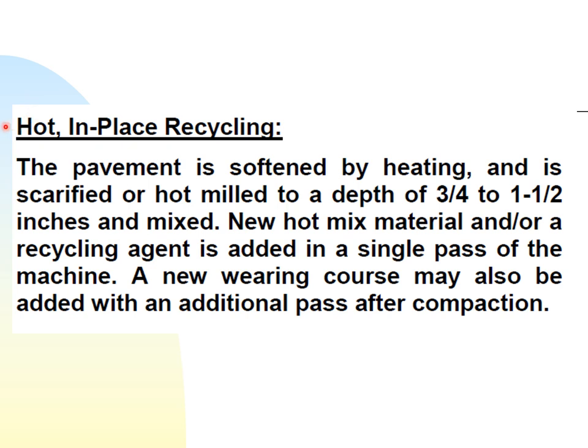Hot in-place recycling. The pavement is softened by heating and is scarified or hot milled to a depth of 3/4 to 1.5 inches and mixed. New hot mix material and or a recycling agent is added in a single pass of the machine. A new wearing course may also be added with an additional pass after compaction.